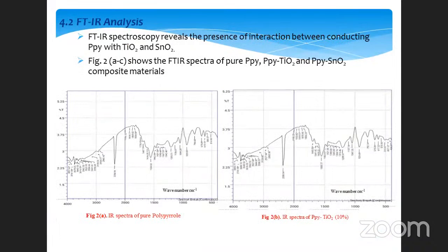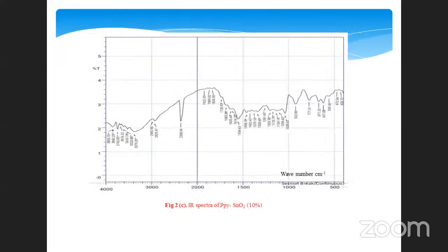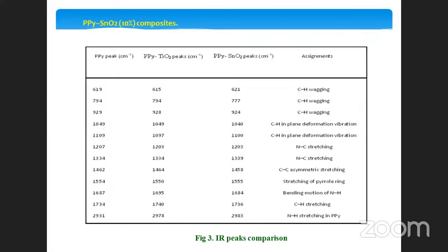These are the FTIR spectroscopy results, which reveal the presence of interaction between conducting polypyrrole, titanium dioxide, and tin dioxide. Next, please. I have drawn the conclusion that on the left-hand side, polypyrrole absorption peaks are shown. These polypyrrole absorption peaks are shifted when TiO2 and SnO2 are composed inside the polypyrrole matrix. And the wave number peaks from 619 to 924 show the CH wagging inside the chain. And 1049 to 1100 conclude the CH in-plane deformation vibration. And other conclusions can also be drawn. Next.